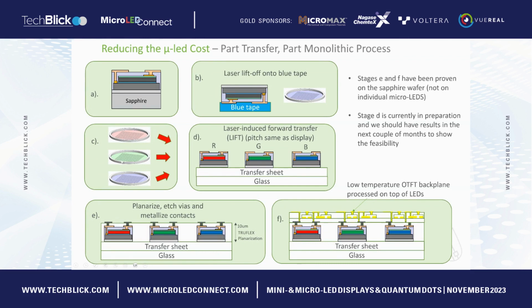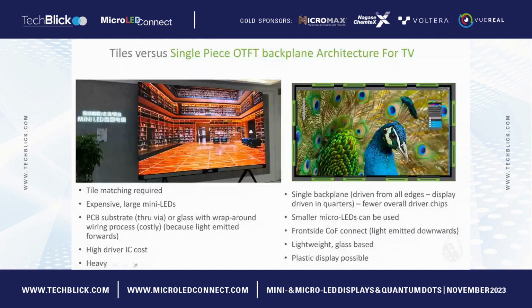So we think there is a good combination of the two processes by using part mass transfer, where you can put the flip chip devices onto a transfer sheet so they're spaced out. Therefore, you can use the LEDs very efficiently. You then planarize them with a thick dielectric material and form sputtered contacts, and then build the backplane on top of that as well.